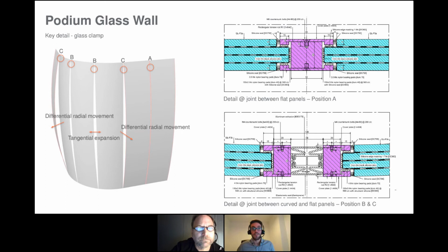For this reason, once we identified these positions, we also had to develop some details that were able to cope with this expected differential behavior of the structure. At the typical position A, we have the rod that clamps the glass panels, which are recessed, and as we don't expect any differential movement, the rod can be shared by the two adjacent panels and move together. When we go to positions B and C, where we are experiencing some differential movement, either radial or tangential, we have to find a way to accommodate this movement, because trying to drag the two panels together, because of the huge displacement and the height and the load, was basically impossible.